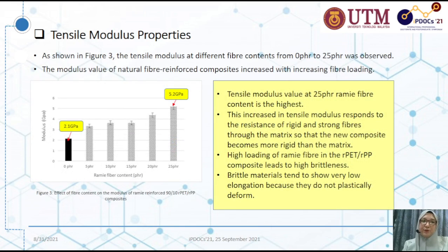Next is tensile modulus properties. As shown in figure 3, the tensile modulus at different fiber contents from 0 pHr to 25 pHr was observed. The modulus value of natural fiber reinforced composite increased with increasing fiber loading. Tensile modulus value at 25 pHr Rami fiber content is the highest at 5.2 GPa.